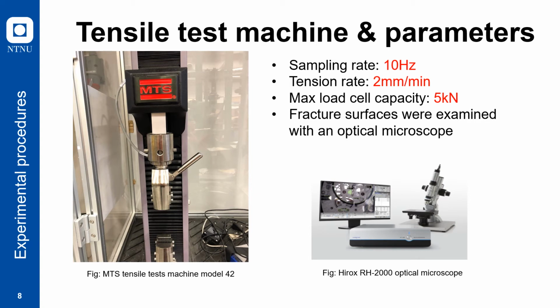And this is the testing machine we have used. It's called MTS Tensile Test Machine Model 42, and it has the maximum load capacity of 5 kilonewton, and this is very suitable for doing the uniaxial tensile test. The sampling rate is 10 Hertz, which means we're recording 10 data points per second. And the tension rate for this test, we have selected 2 millimeter per minute for the PLA, and the fracture surfaces were also examined with a microscope.